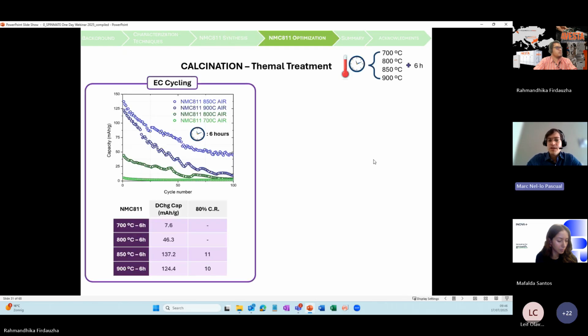We started with 4 different temperatures that were 700 degrees, 800 degrees, 850, and 900 degrees for 6 hours. So these are the electrochemical results, and what we observed was that 700 and 800 degrees didn't give any good capacity, and it was not until we got into higher temperatures, 850 to 900, that we started to get some better results. In the case of 850, this is the one that gave a higher discharge capacity, a value close to 140, with a capacity retention of 11 cycles. However, this is not a really good performance, so we needed to check what was happening, and to do that, let's dive into the physicochemical analysis.